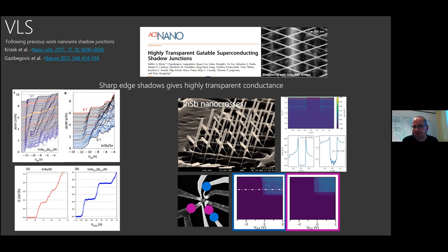Let me ask a follow-up on this, actually. You mentioned that this exact band structure depends on the aluminum layer thickness quite a lot. So what happens if you average out for an inhomogeneous layer thickness? Yeah, it seems like we need a homogeneous layer and a single type of crystal structure before we see the bands of aluminum. Even if you have a flat, thin layer of aluminum, we don't always see it. It seems like it needs to align with the semiconductor in a well-defined way. If it's slightly misoriented, then it's also difficult to probe it in ARPES at the same time as the indium arsenide. I see.